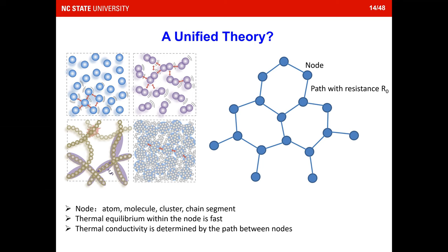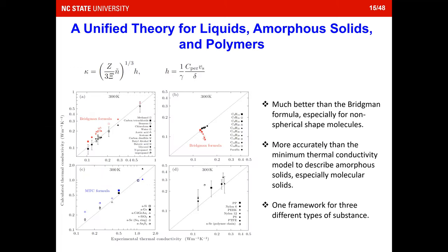So I actually skipped a lot of slides because there are a lot of details here, but the result looks pretty good. We did find a unifying theory to describe liquid, amorphous solid, and polymers. If you're interested, you can look at our recent papers. So the result is shown in the left-hand side figures. As you can see, all these black dots are experimental data, and they match our models.